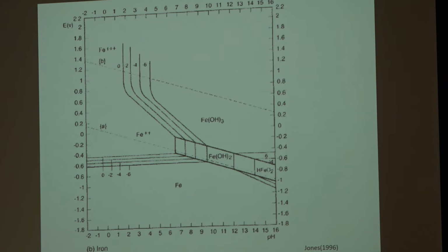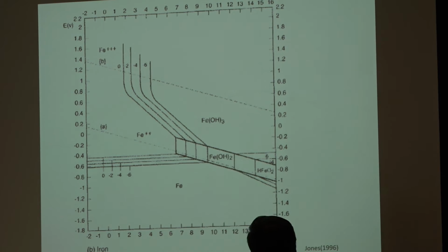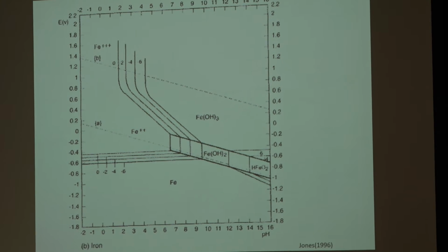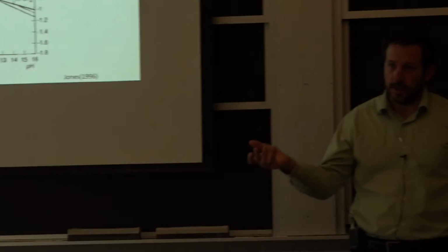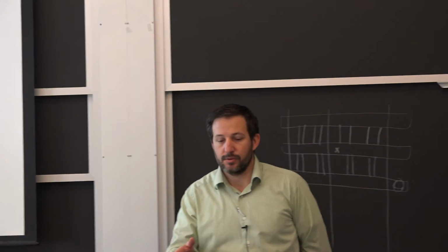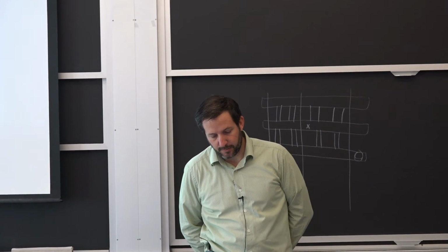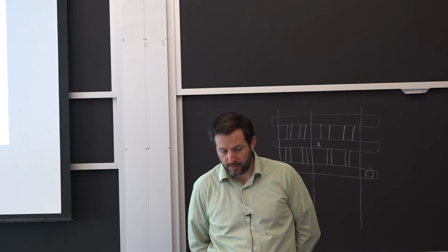It will work very well if that's this region here, pH 10 to 12, as long as you don't have a degradation of the concrete. So if the concrete starts to crack, even if it's a little amount, and now you have water penetration and you lose this high pH where the rebar is, then now it starts to corrode and spall. So it's a major issue for the use of steel as a reinforcement, because you always end up with some degradation of the concrete if you have cycles, especially thermal cycles and history and different loading, and it's a big structure.